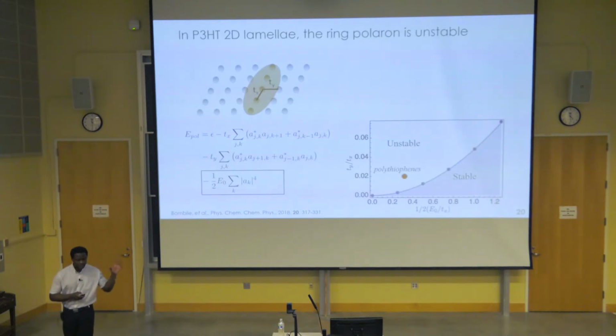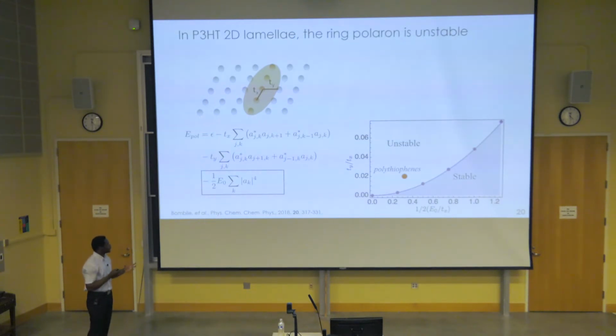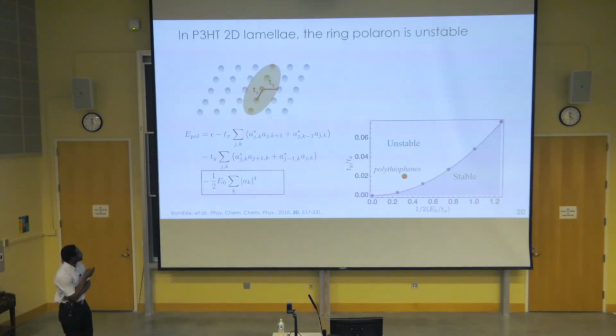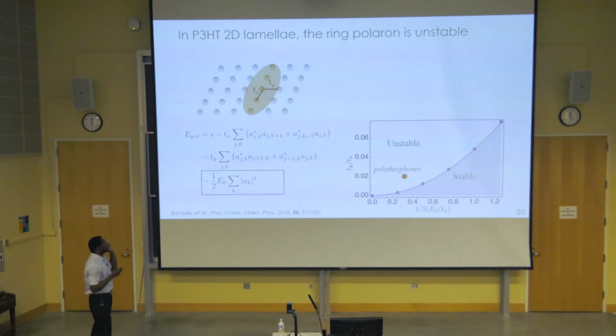So we've also extended this analysis to a two-dimensional lamella, where in addition to the carrier hopping along the chain, it's now able to hop between chains, and therefore we have an additional term here that wants to delocalize the charge carrier, and we still have our stabilizing term that comes from the reorganization of nuclei. And what we observe for this system is that the polaron binding energy is positive, meaning that the polaron will not form in this system for P3HT.